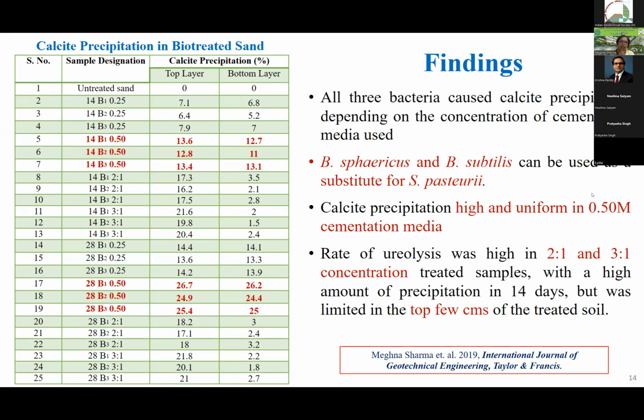So here in this study, what I found is that all bacteria worked well. Okay, so Bacillus subtilis and Bacillus sphaericus can be used as a substitute for this especially, but coming to the concentrations of urea and calcium chloride dihydrate, the equimolar concentration of urea and calcium chloride dihydrate at 0.5 molar concentration resulted in uniformity in calcite precipitation.